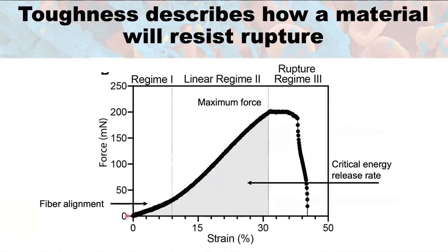properties. So again, if we look at the force, which can be seen here on the Y ordinate versus the strain on the X ordinate, we're able to look at that fracture curve, just like we saw on the previous slide. And so we can see that the force initially increases, right? It then plateaus and starts to decrease. And so if we want to look at the toughness of the material, or the ability of the material to absorb energy and deform without rupture, then we're going to look at the part of this curve that starts from our zero point up until our maximum force, and use this to calculate the critical energy release rate, or the rate at which energy is dissipated to create a new fracture area.